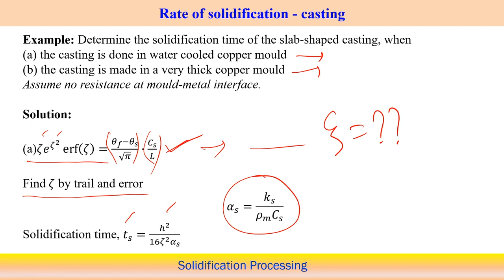But in the second one, we do not use the very thick copper mold, and we are not using any kind of water cooling. So in this case, both the contact resistance components have to be considered in the second case as compared to the first case, because the first case is only the resistance because of the solidified depth of the solidification; what is the contact resistance offered by this, we need to consider that only. But in the second case, both the resistance through the mold metal surface, mold thickness, as well as the solidification depth, both components we need to consider in the second case.